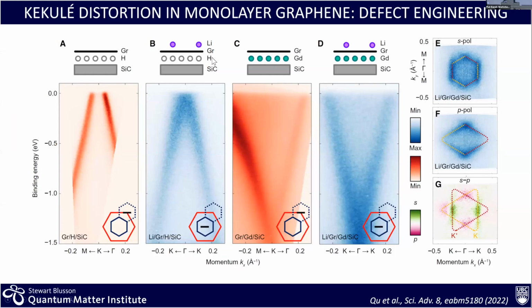So basically, that's your question. The way to change the doping, because really the question was, is this due to nesting, or is it due to something else? The way we did it was to look at a different system. You're looking at graphene, and then you have hydrogen intercalation, or gadolinium intercalation. So, different forms of intercalation. In one case you can get excessive doping, even larger doping. But with the other one, you can p-dope the system. And in fact, we see exactly the same effect on all of them.